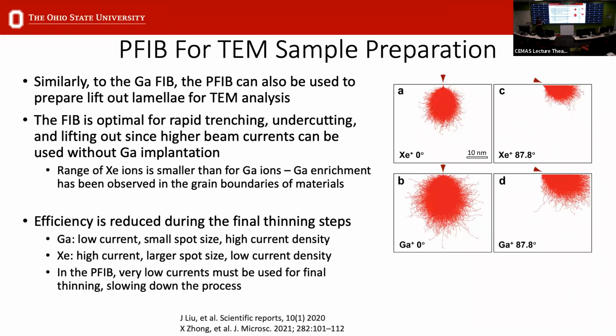The trade-off is that when you do go to the final thinning, the gallium FIB has low currents, small spot size, and a high current density, which makes it good for precision thinning. When doing xenon, you have a high current, larger spot size, and a low current density. So in this case, it's difficult to precisely thin your sample, and to do it takes more care. You have to be a little bit more careful for this.